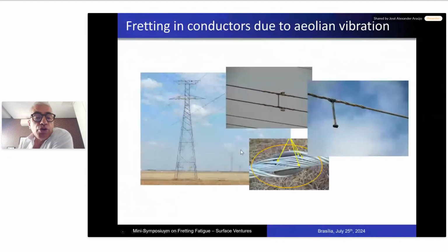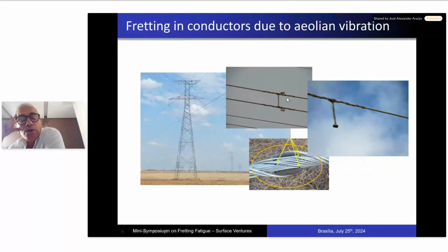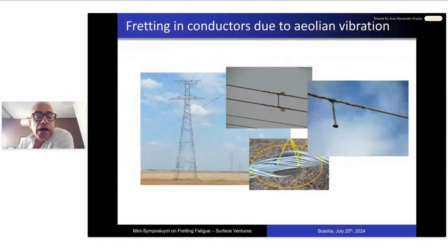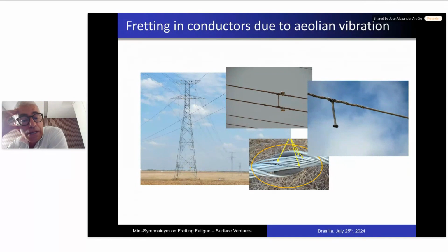Here I'm showing you a real problem that we got here in the Central West region of Brazil, where you can see we had a twin vertical conductors configuration. In this line, you can see that the terrain is very flat. So this type of terrain is very dangerous for fretting fatigue problems because you develop laminar winds. And then with these laminar winds, you have the formation of these vortices that will provoke this high frequency, small amplitude movement of the conductor.